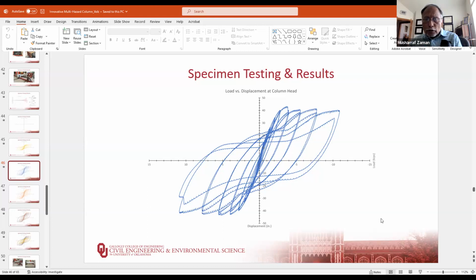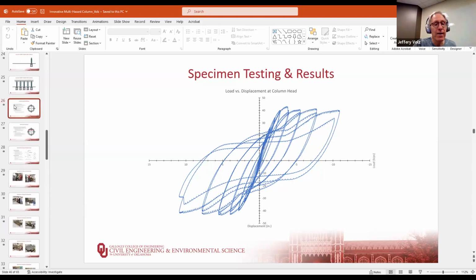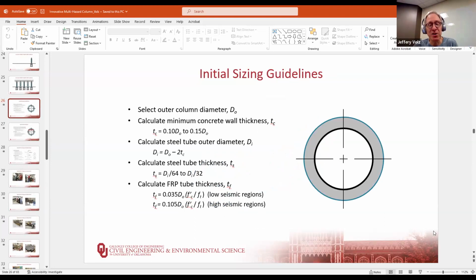So I think the next one is also kind of related: is there any particular reason for the thicknesses and the dimensions that you selected for your testing? Yes, we went by the current design guidelines, these initial sizing guidelines, which let me jump back to this. Again, they give you a start. But you have to pick an exterior diameter. That has to be your starting point. So again, in an actual column, you could use roughly the same diameters as you would have selected for a reinforced concrete column as a starting point. And then from there, you follow these guidelines. They give you the thickness range for the concrete, the diameter and thickness range for the steel tube, and of course the diameter and the thickness range for the FRP tube.